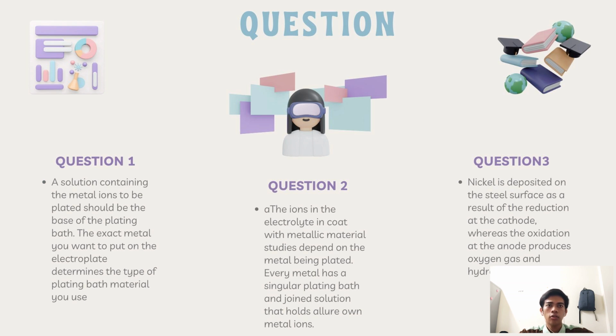Third, give all relevant half reactions occurring at the cathode and anode for the mild steel sample. Nickel is deposited on the steel surface as a result of the reduction at the cathode, whereas the oxidation at the anode produces oxygen gas and hydrogen ions. Through the regulated transfer of metal ions from the electrolyte to the mild steel sample made possible by these reactions, the steel surface becomes nickel plated.